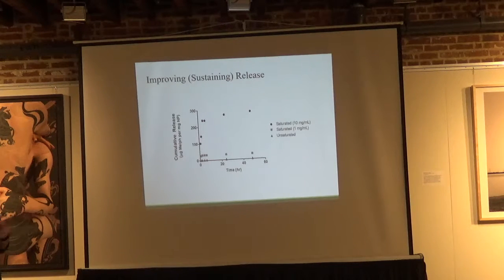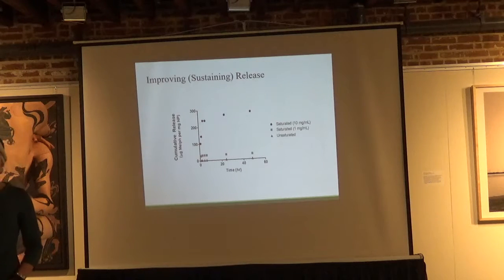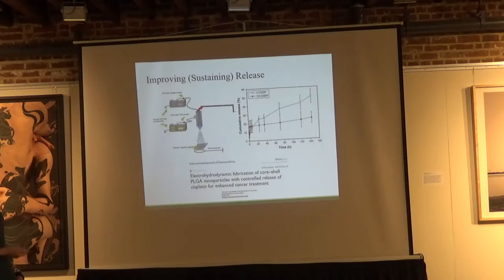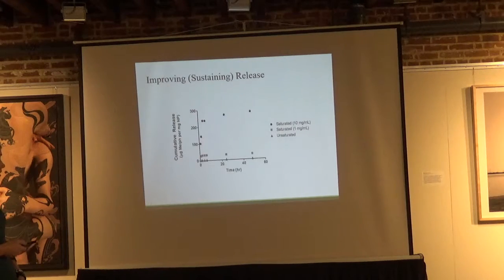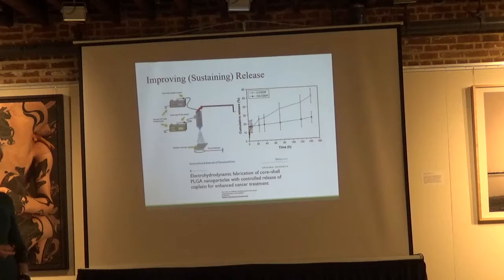But to show you kind of a worst case example for delivery of a small molecule, small hydrophilic chemotherapeutic, here's a plot we have. We were delivering melphalan for ocular cancers. And you can see that regardless of formulation, really within the first few hours, all of the melphalan is coming out. And moreover, due to our fabrication process, the emulsion-based process, we're losing a lot just while we fabricate the particles. So we started thinking, based on other literature, how can we improve our sustained release characteristics over time and make it come closer to zero-order-based release mechanisms.